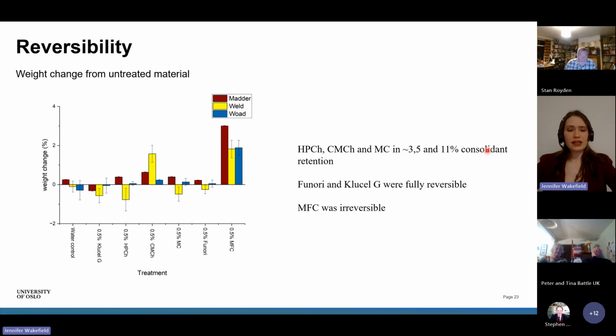So in terms of the reversibility, I was looking at seeing whether the treatments were reversible or not, and wanted to see if you could wash out the consolidant effectively. So we're looking at the water control. So we looked at washing out. We're comparing the weights before it was treated to after we washed out the material, to see whether it came back to the original weight before it was treated or not.